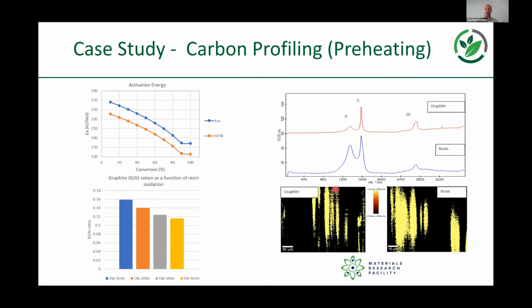And what's interesting about that is that we're actually able to do it in a spatially resolved way as well, which is neat and fits back into some of the challenges that we've seen with our X-ray CT analysis of these materials, because it allows us to differentiate on a spatial basis between the graphite and the resin and how those two things are being attacked. And we're now moving on to look at how we can connect that back to the X-ray microscopy and learn much more about how these materials behave.